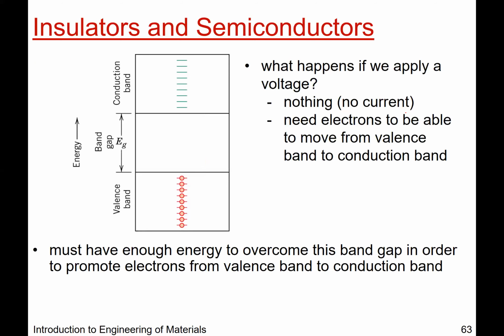It could just be thermal energy, right? Thermal vibrations, kT, you can just have enough energy at room temperature for electrons to be excited if your band gap is small enough. And with silicon and germanium, silicon has a band gap of about 1 eV, germanium is about 0.6, 0.7 eV. And so thermally at room temperature, there's always some fraction of the population of electrons that will be thermally activated, thermally excited. But if you want a higher concentration and in a controlled way that you want excitation, then you're going to have to do something.